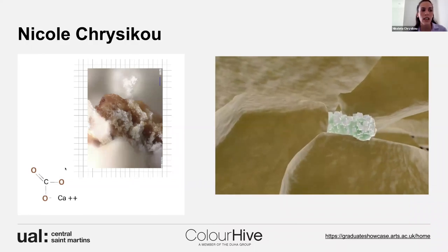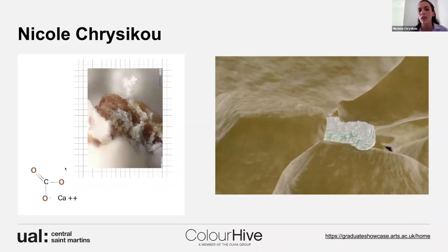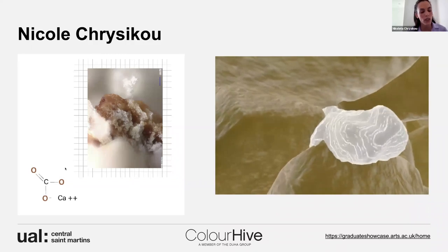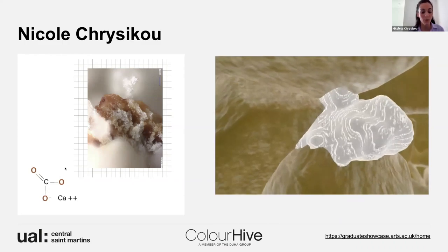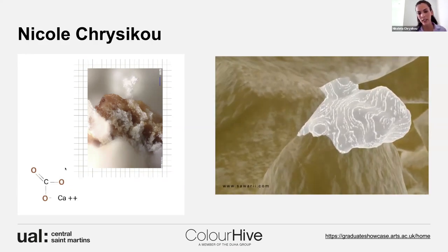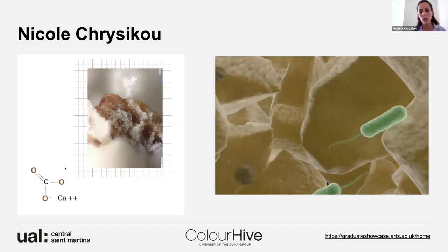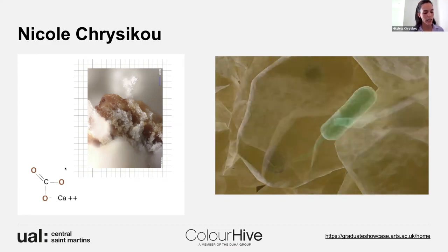It's a process that scientists have been researching for the last 10 years, mainly geologists, for soil reinforcement, for self-healing concrete or biobricks. So this is a process by which living organisms produce minerals to harden existing tissues. What happens is the bacteria are pumped into the aggregate and establish themselves between the grain particles. And when calcium chloride is added, the bacteria produce calcite, which is a sticky substance, let's say, that glues the